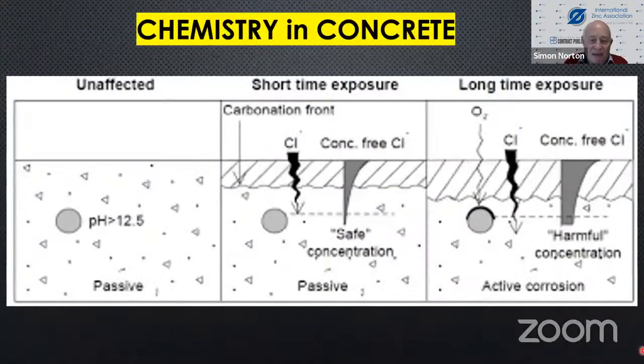When zinc is inside concrete and you use reinforcing steel, before it's coated, there on the left-hand side is the pH greater than 12.5 in concrete. In cement, obviously, it has that pH. The rebar is inside here, and this is a passive structure. Then with time, your concrete gets carbonated by carbon dioxide from the atmosphere, particularly at the coast, or if it's an area where there's high winds. If it's the coast and it's marine, there's going to be chlorides. And if you look here and you take the depth of concrete and you take the concentration of chloride, there it's high. And as you go into the concrete, it gets lower and lower. So initially, this pH here will change, but this part of the concrete is safe.